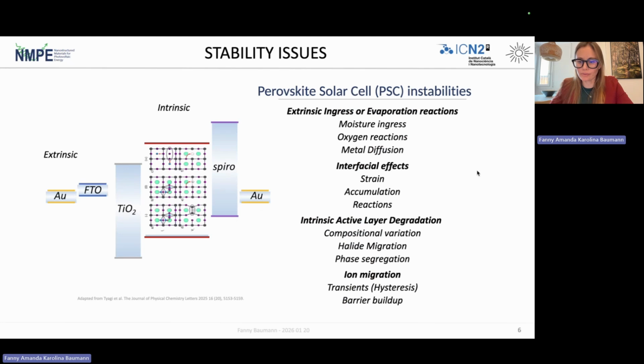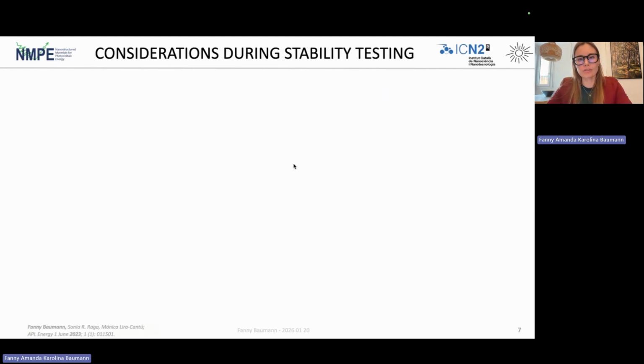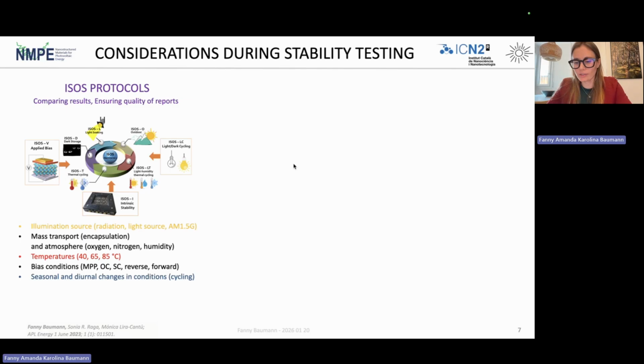It is indeed important to focus on stability, as perovskite solar cells are presenting several types of instabilities, some extrinsic and more intrinsic degradations, which have been treated to a larger and smaller extent. So we are going to focus quite a bit on intrinsic instabilities today. And some other things to take into account during stability testing is the adherence to the ISOS protocols so that we can ensure the quality of the reports, and we can also compare results between laboratories.